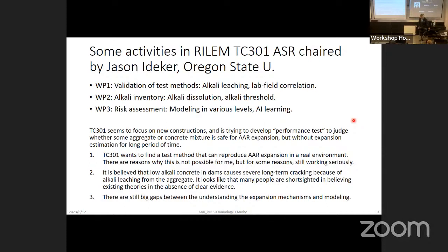For the second, I want to explain a bit more. In dam concrete, the alkali content is very limited. Even in such concrete, it expands over a long time. So some researchers proposed a hypothesis that some kind of mineral, such as feldspar, releases sodium from the aggregate, and then this sodium can accelerate ASR over a long time. But for me, it looks like only a hypothesis. There is no direct evidence for me.